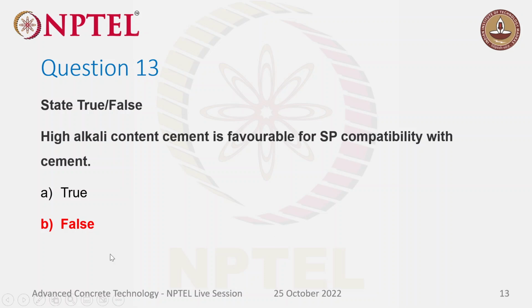It's not true because high alkali content will affect the workability. Even high alkali cement is not favorable for workability, so it also affects the SP compatibility with cement. So one of the techniques to reduce the compatibility issues is to reduce the alkali content and also moderate the fineness. Normally fineness is related to reactivity, right? Increasing the fineness will increase the reactivity, but increasing the fineness is not always favorable. We have to moderate the fineness of cement such that there is no compatibility issue between the SPs and the cement, because high fineness leads to absorbing more SPs for the given workability. If it absorbs more SPs than required due to fineness, then obviously we can get the workability, but in the end it will cause retardation as well. So we have to think about different elements when it comes to workability.